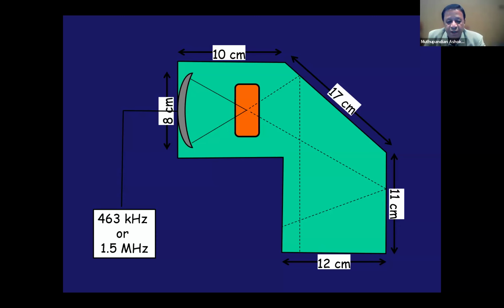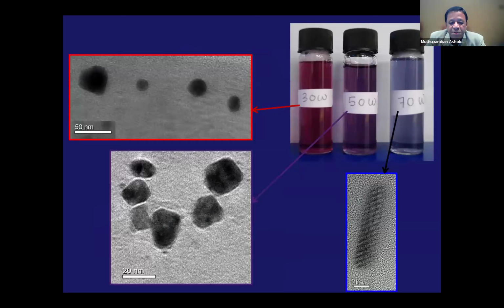But here we are using high intensity focused ultrasound for the purpose of controlling the shape of the particles. For example, by changing the power using the HIFU, if you use 30 watts, we can get spherical particles. If you use 50 watts, we can get octahedral particles. If you use 70 watts, we can get cylindrical or rod-like particles. And again, those who are working in nanomaterials know the color of the solution is influenced by the shape and size of the particle. So you can see that when it is spherical, it is kind of pink in color. When it is rod-like, it is blue or purple in color.